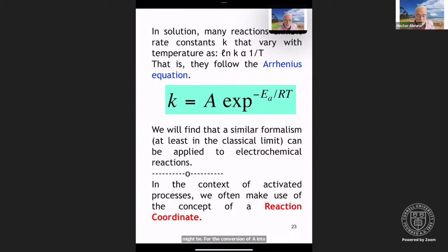what barriers might be for the conversion of A into B and B into A. Now, in solution, many reactions have rate constants that vary with temperature as natural log of K proportional to 1/T. That is, they follow the Arrhenius equation. So we write K equals A, typically the so-called pre-exponential because it comes before the exponent, and then some term that relates activation energy divided by RT to put it in the right units. And so we will find that a similar formalism, and I mention here, at least in the classical limit, meaning no tunneling, can be applied to electrochemical reactions. And so in this context, an activated process means that you have to overcome a barrier, which is inherent in this Arrhenius expression.